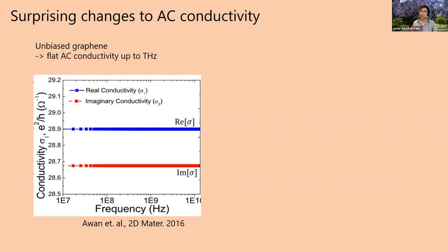Another thing that was weird is that we could also measure the AC conductivity. The AC conductivity should be very much related to the AC noise, so it's important to measure both of them. We didn't expect to see much, because in graphene the AC conductivity is supposed to be completely flat, going up to very high frequencies like terahertz, because graphene is a pretty boring material for the most part in terms of its frequency dependence.